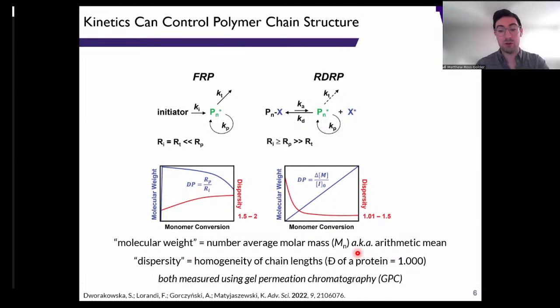Both of these measures, both molar mass and dispersity, are going to be measured in the subsequent slides using a technique called gel permeation chromatography or size exclusion chromatography. And this is going to separate out molecules based off of their size. So going through a size exclusion column, molecules that are really, really large will elute faster as they don't get trapped in the pores. Molecules that are much smaller will get trapped in the pores more readily and traverse through the column much slower.